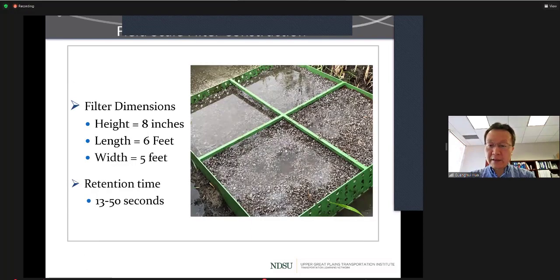And this figure shows the construction of the field scale filter. We use a steel structure to contain the filter media. And the steel structure has a height of 8 inches, length of 6 feet, and a width of 5 feet. And during the storm runoff treatment, we measured the flow and compared the porosity of the media. We determined that the retention time was somewhere between 13 to 50 seconds.